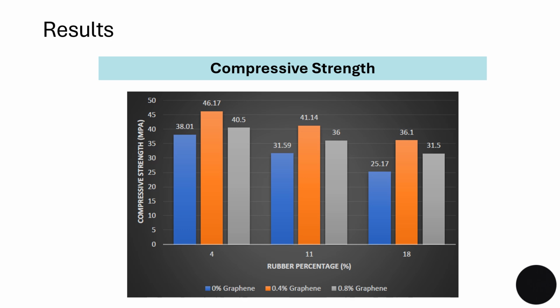You can see the compressive strength without rubber, without graphene, is 38 megapascal. With only a low content of rubber, 4%, with the increase of rubber to 18%, the strength reduced to 25 megapascal. But with the addition of 0.4% graphene, we can get a compressive strength of 36 megapascal, which is higher than the design strength of 35 megapascal. It means with the combination of 18% rubber and 0.4% graphene, we can get 36 megapascal compressive strength, which is higher than the design strength of 35 megapascal.